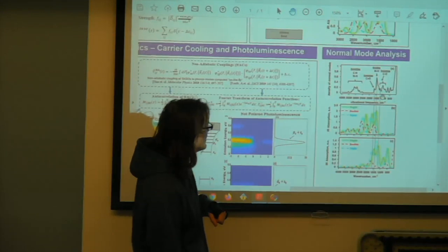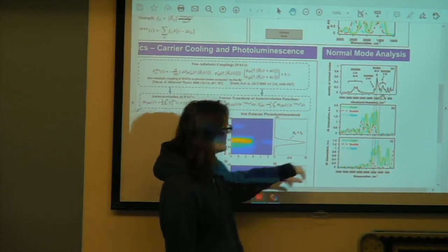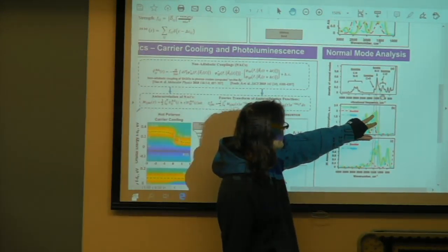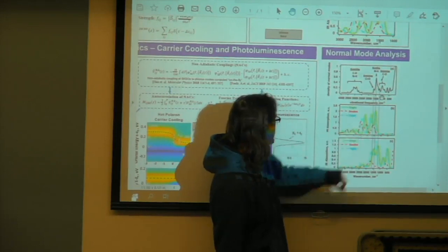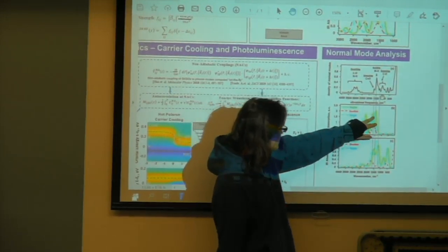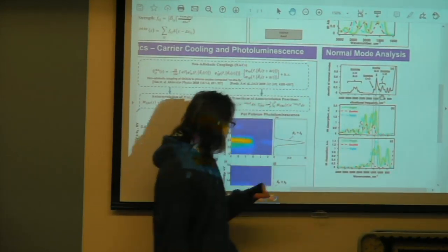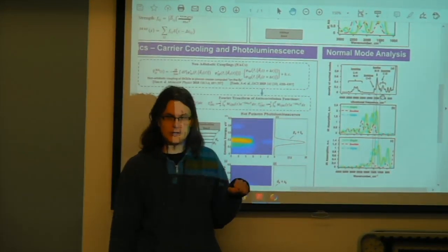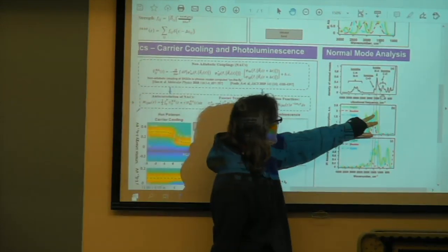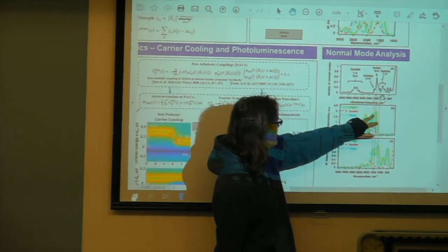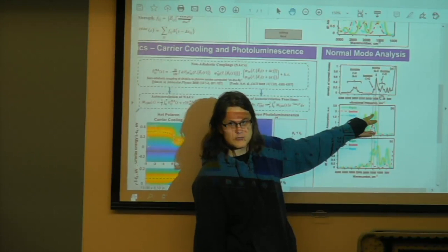Essentially what we see is that the carboxylates are in resonance with the triplet polaron, which from the table I showed before was the worst emitter compared to the singlet. So it's off resonance with the singlet, but in resonance with the triplet.